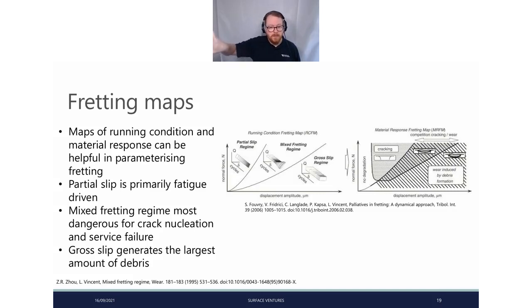So if we were to increase that displacement amplitude, we could then add another line and say, okay, this is full sliding. And then we have our material response, which I've alluded to a little earlier. With partial slip, because there is such little movement, this is fatigue driven. We can think of this in terms of low cycle and high cycle fatigue. Low cycle fatigue typically has higher load and a much shorter cycle time, of course. High cycle fatigue is very crack driven, with lower loads and much higher cycles, in the hundreds of thousands versus just maybe thousands for the other fatigue mode.